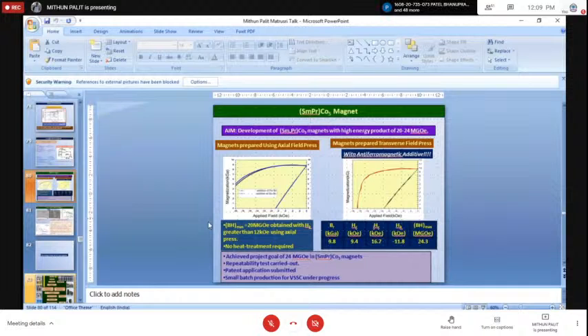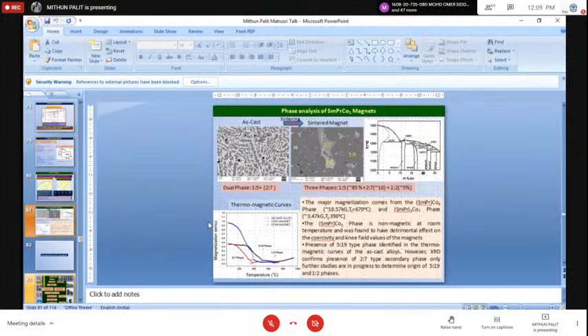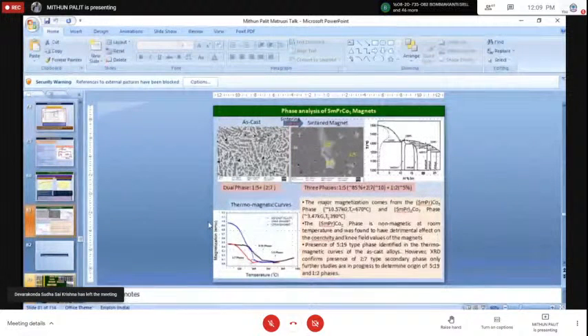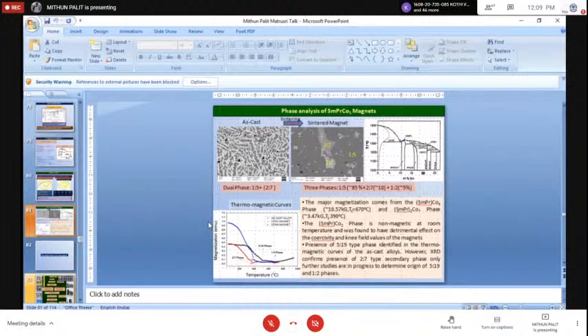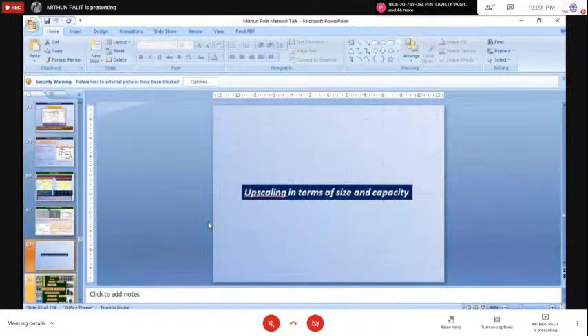And this SmCo5 magnet, we wanted to improve its property further, and accordingly Pr has been used, and by doing so we could increase the energy product up to 24 megagauss-oersted, which is remarkable in this class of system. And here also the reason for the high magnetic energy product in this Pr added system stems from the microstructural engineering. We could form some 2-7 type phases, which are also present between two SmCo5 particles, and they have very good shielding strength. They shield between two particles, and accordingly the magnetic energy product is good.